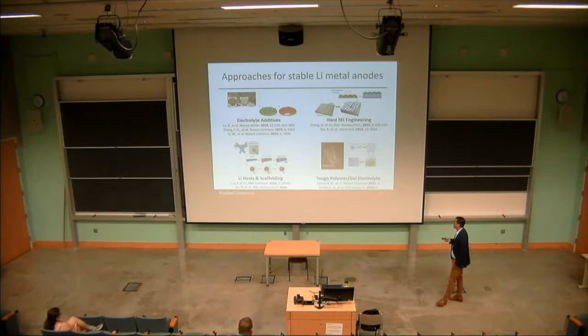And then finally, tough polymer and gel electrolytes. The idea here came out of some work from John Newman's group where they found that a modulus of about 7 gigapascals would mechanically suppress a dendrite.